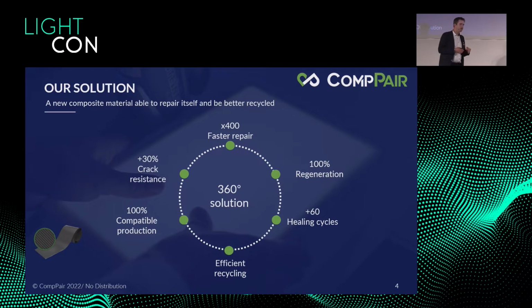Something that was really important for us, and you know that we have been talking about self-healing composites for many years right now. There were many research as well, and we are coming from EPFL in Switzerland. There were 3-4 PhD theses before mine, and we had always the strategy of bringing fully autonomous repaired composites. Here we change a bit the strategy by saying, okay, let's trigger the healing by heat, but at room temperature, we stay structural and we provide good mechanical properties. And actually, this was the right strategy because now we are able to bring those new functionalities, but while having a compatible production. This is something that is really important for us as well, for all the product families that we are developing, and crack resistance and mechanical properties that are competitive.